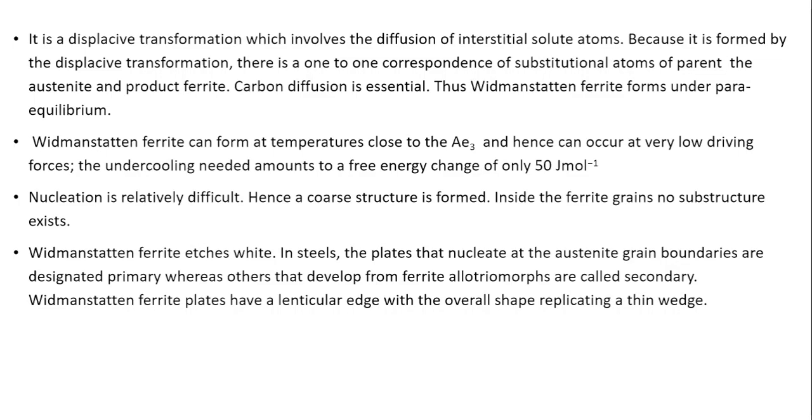Widmanstatten ferrite can form at temperature close to AE3 and hence can occur at very low driving forces. The undercooling needed amounts to a free energy change of only about 50 joules per mole. Because of this small undercooling, the nucleation is relatively difficult. Hence a coarse microstructure is produced.